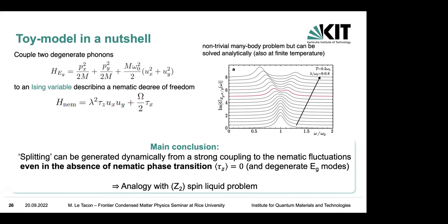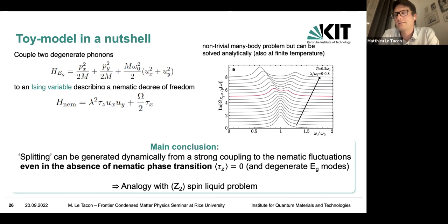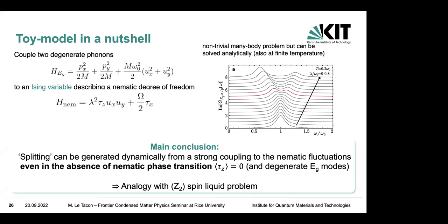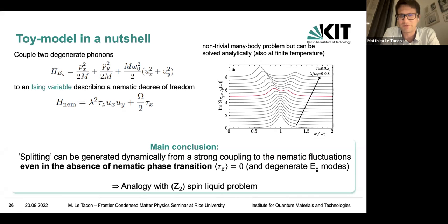Sorry, my original feeling is that in the orthorhombic phase, the Eg will become, let's say, B2g and B3g, but they are still not B1g. Okay, well, this we can talk about, but this is a different thing. The B1g in the orthorhombic phase is now called Ag, so it's a different nomenclature. But if you just take the tables of characters and look at what's possible, what symmetry couples to Eg modes, it just happens that the B1g does.